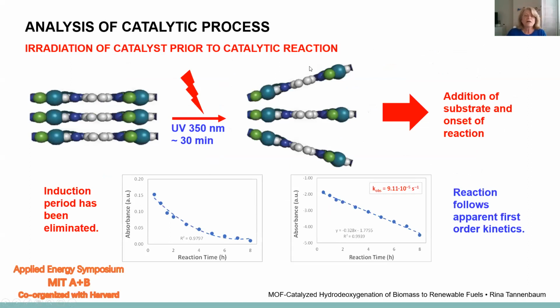Okay, so because that is something that we have to take into account, we have irradiated the stacks by UV at 350 nanometers, and we've learned that this actually is the appropriate energy to eliminate the stacking interactions. And so we irradiate for 30 minutes prior to reaction. And then what we note is that the reaction proceeds in a different manner. Actually, it's a first order reaction without an induction period.